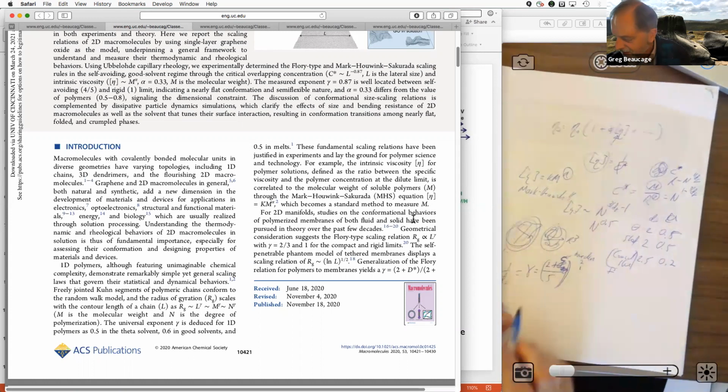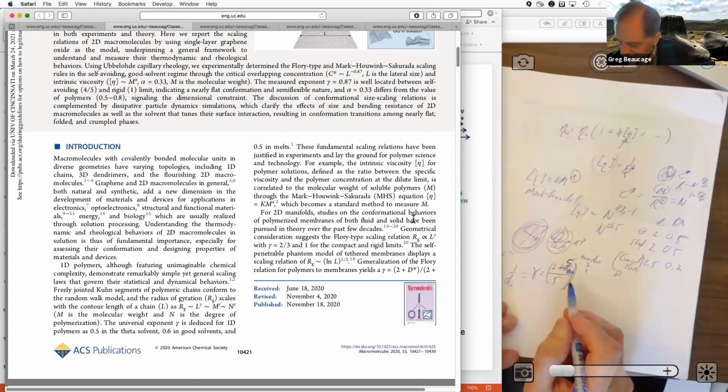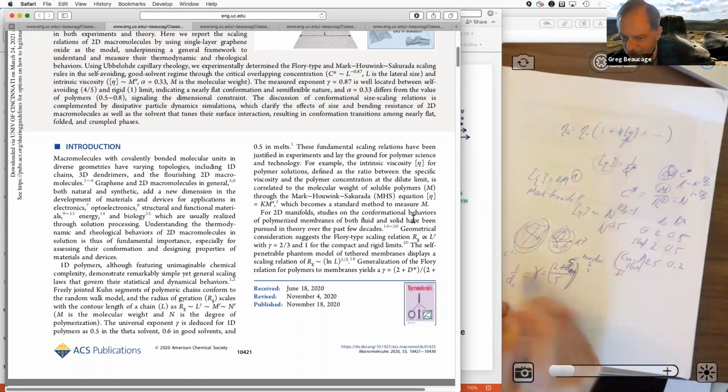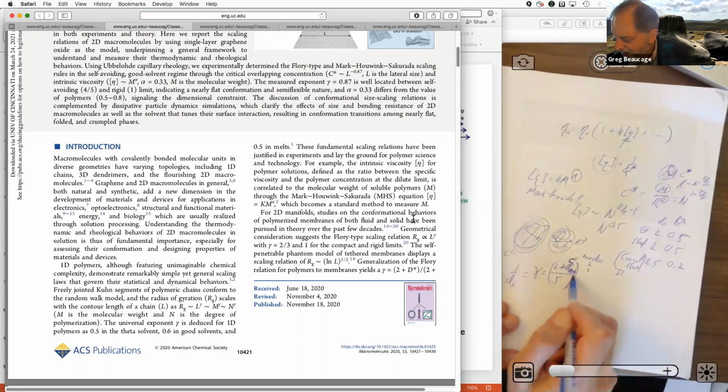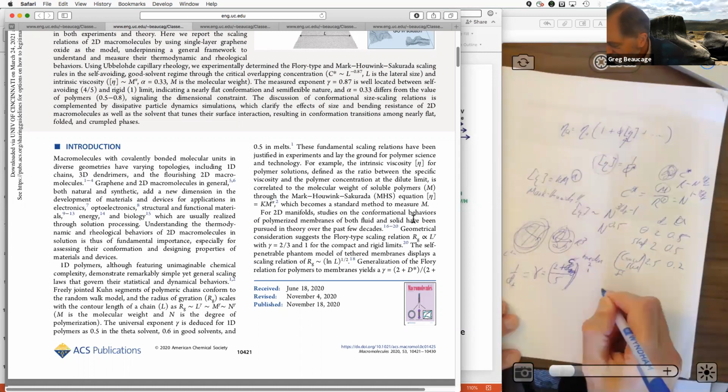So df is 5/3 for a, okay, so this equation works for the Flory-Krigbaum, but basically we know that Flory-Krigbaum is an approximation. So this is an approximate equation. In other words, df should be 1.70, and this thing gives 1.67.